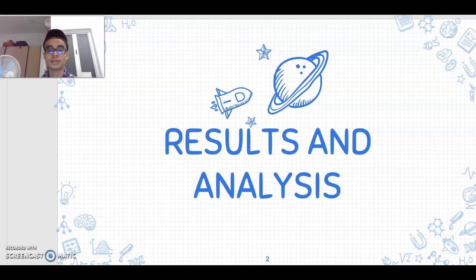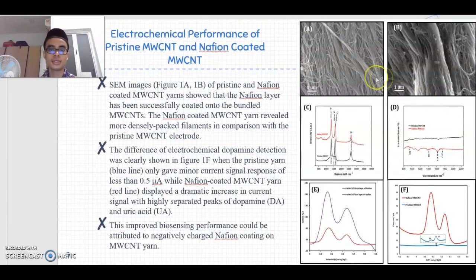Now I would like to present the results and analysis based on the experiment. Firstly, the electrochemical performance of pristine multi-wall carbon nanotube and Nafion-coated multi-wall carbon nanotube. The SEM images of figure 1A and 1B of pristine and Nafion-coated multi-wall carbon nanotube yarns showed that the Nafion layer has been successfully coated onto the bundled multi-wall carbon nanotubes. The Nafion-coated multi-wall carbon nanotube yarn revealed more densely packed filaments in comparison with the pristine multi-wall carbon nanotube electrode.